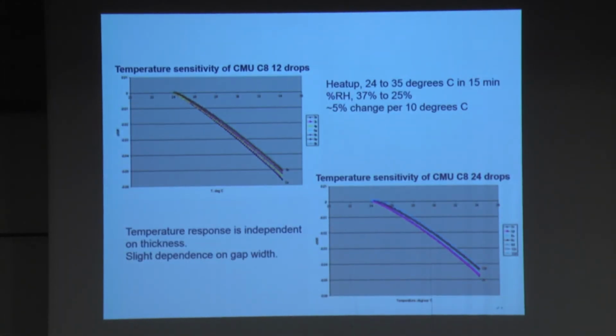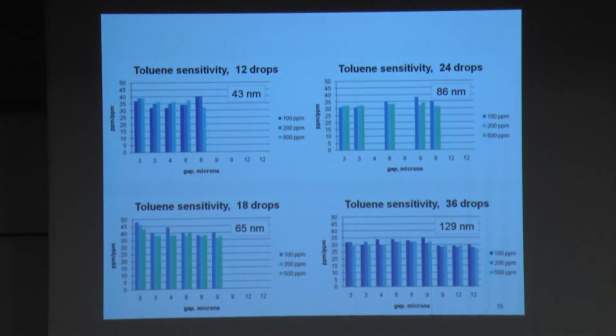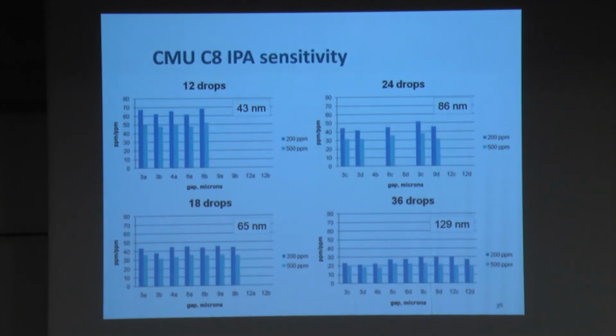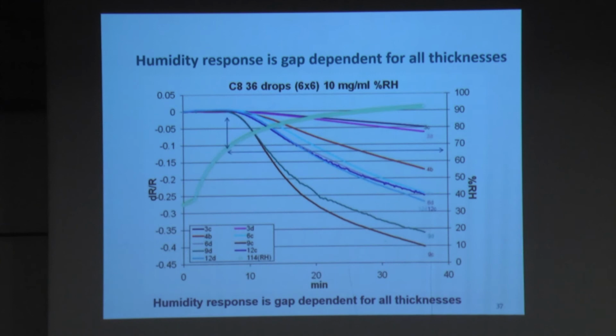temperature response doesn't show any gap effect, a very small one. Toluene response also doesn't show any special gap effect. Now, look at the beginning. When the films are very thin, you cannot measure the resistance on the wider gaps because resistance is higher than 120 megaohms, which is the limit of the instrument we were using. However, when you increase your thickness, you can see a very nice response, and there's no basic difference between them. The same is true about isopropanol. I won't talk about it later.